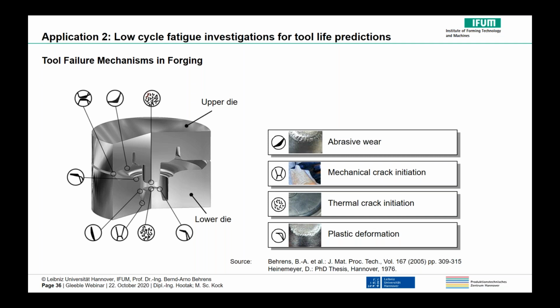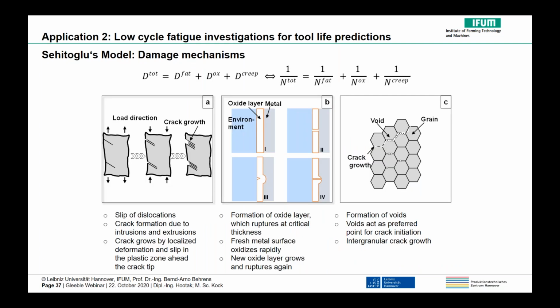So next, we need an approach to calculate damage in the tools, such as the tool life prediction approach, which takes three different mechanisms into account. So the total damage is calculated by the sum of the corresponding proportions, of which the reciprocals are the cycle numbers until crack initiation. Fatigue damage is represented by the classical fatigue mechanism, which normally occurs at ambient temperature.